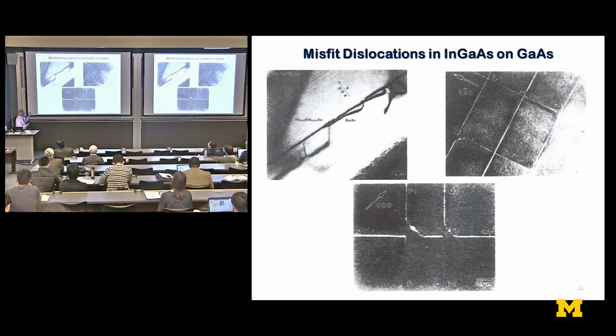with Ron Gibala, and we shared a very smart student, Kevin Chang. I mean, they're all smart. But this is some of his work out from textbooks. He was looking at the formation of dislocations and the critical thickness of strained pseudomorphic layers and strained layers. And this is, you can see, the misfit dislocation network. This is all his work. Of course, with me, he also made transistors out of these heterostructures and so on. So that was what got me started with strained semiconductors.